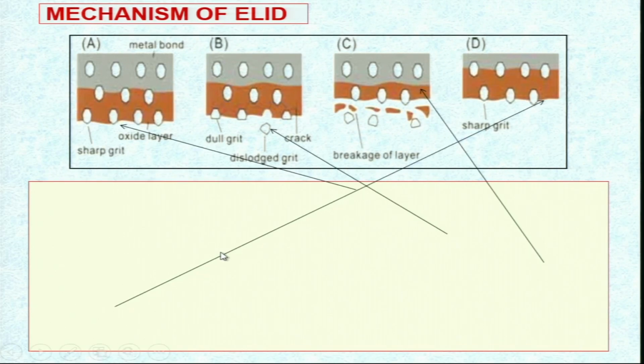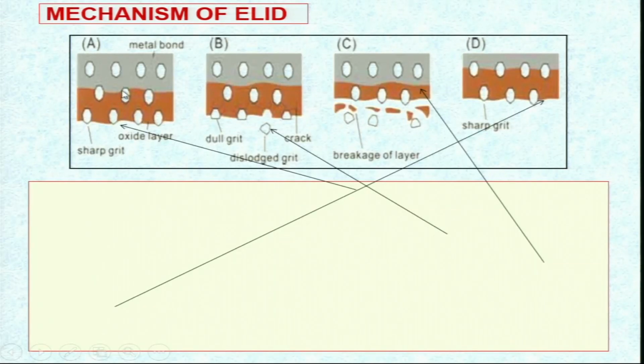Mechanism of ELID. Now, this is a very important slide to understand the mechanism of ELID grinding, dressing. Now, this is the metal bonded grinding wheel. This is the metal bond and these are the abrasive particles which are electrically non-conductive. Now, when electrolyte is being supplied over this, then an oxide layer is formed due to the electrochemical reaction, as you can see here, and definitely this oxide layer is weaker than the parent metal bond, and these are the sharp grits and they are going to perform the dressing or grinding process.